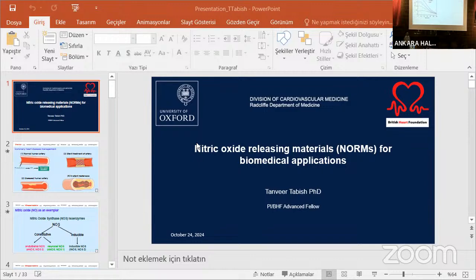So this is the nitric oxide production levels. If we use just the source of nitric oxide, that's in red color, you can see that it can also produce nitric oxide, but only up to 20 nanomolar. That's not really therapeutically relevant. If we use this polyethylene glycol graphene oxide in the presence of the nitric oxide source, we can produce up to 80 nanomolar per second. That's what we want to achieve. So that's why we need different sources and different catalysts to achieve this.